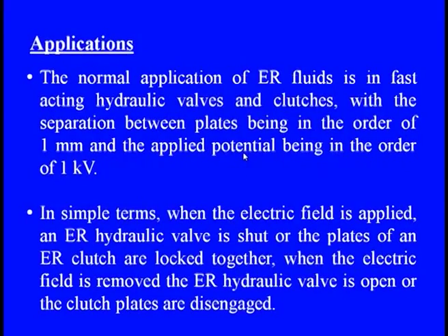The normal application of this ER fluid is in fast acting hydraulic valves and clutches, with a separation between the plates of about 1 millimeter, where we can apply an electric field of almost up to 1 kilovolt, and we can directly apply this in actuation or sensing parts under hydraulic valves or clutches.